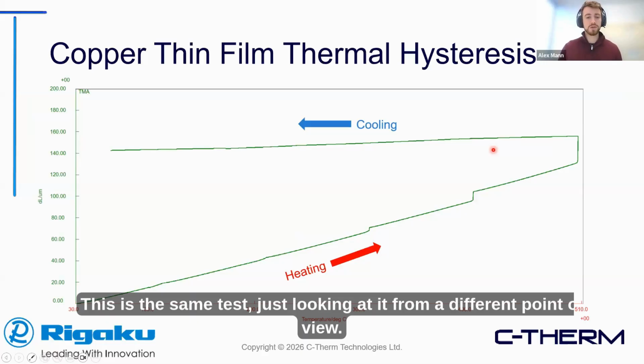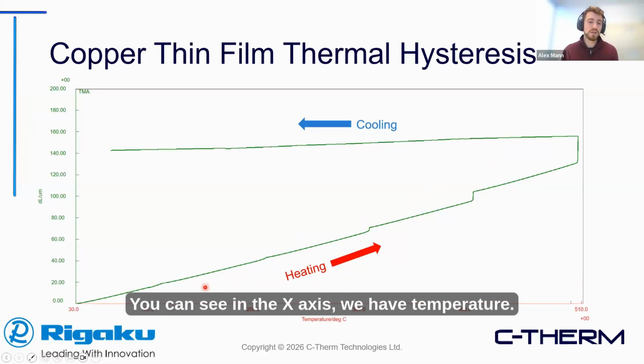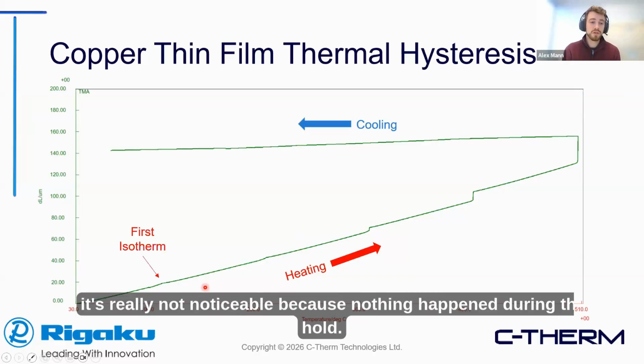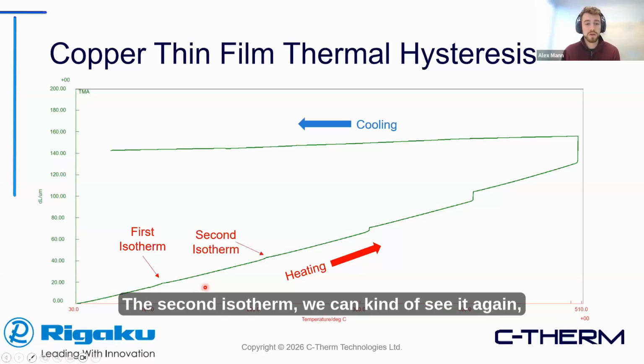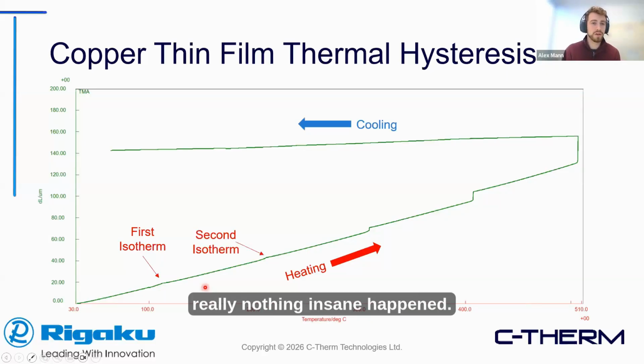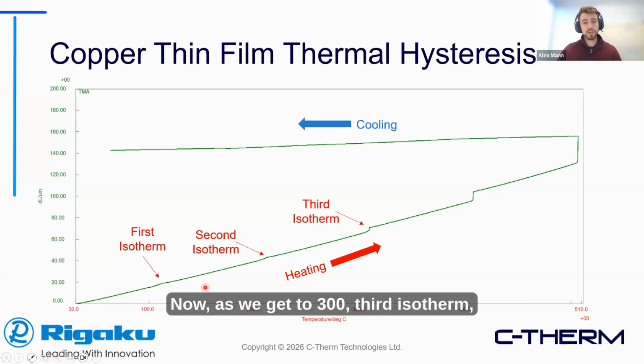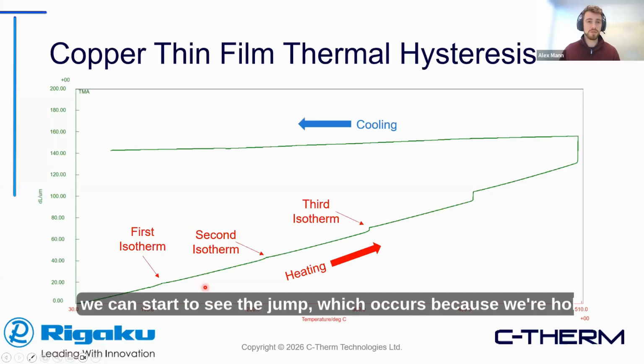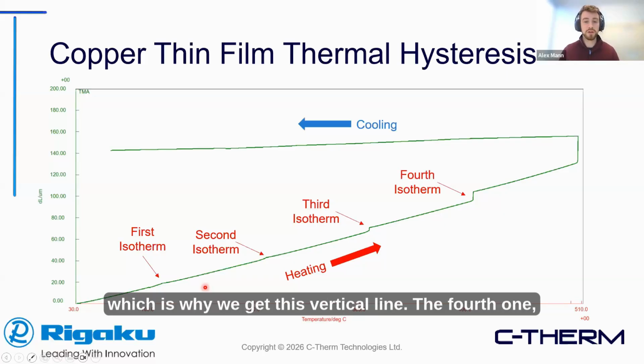This is the same test, just looking at it from a different point of view. You can see on the x-axis, we have temperature. So the first isotherm, it's really not noticeable because nothing happened during the hold. The second isotherm, we can kind of see it, but again, really nothing insane happened. Now, as we get to 300, third isotherm, we can start to see the jump, which occurs because we're holding, so the temperature isn't increasing, but we're still expanding, which is why we get this vertical line.